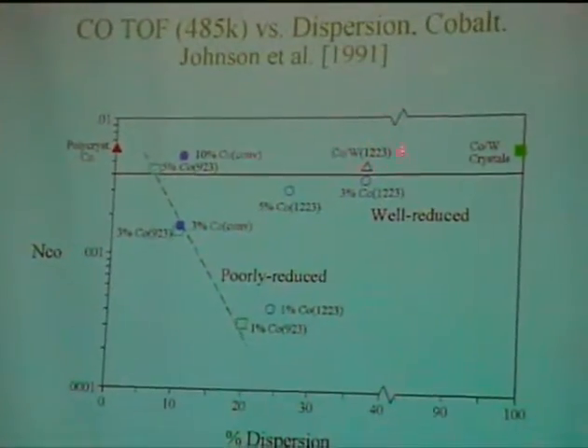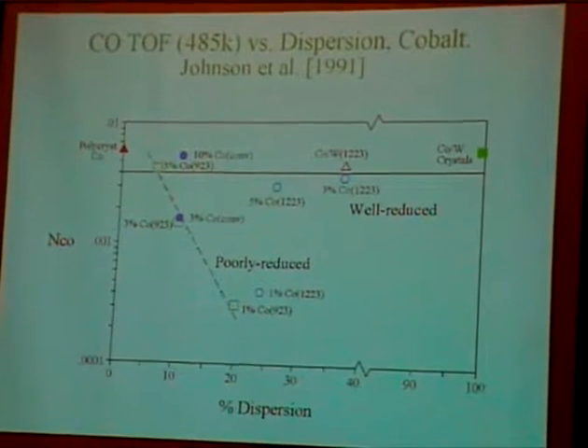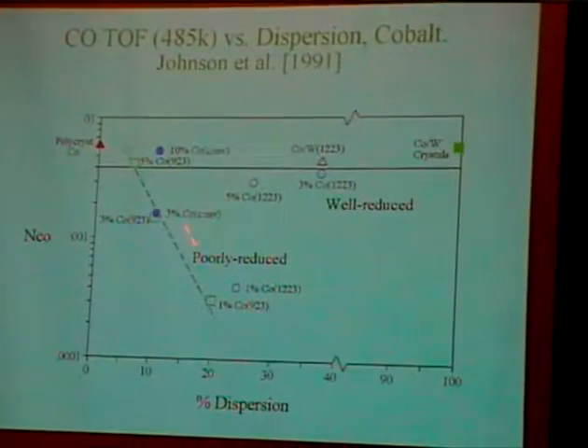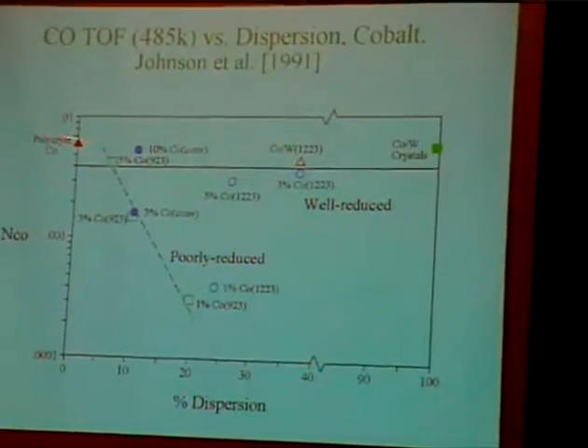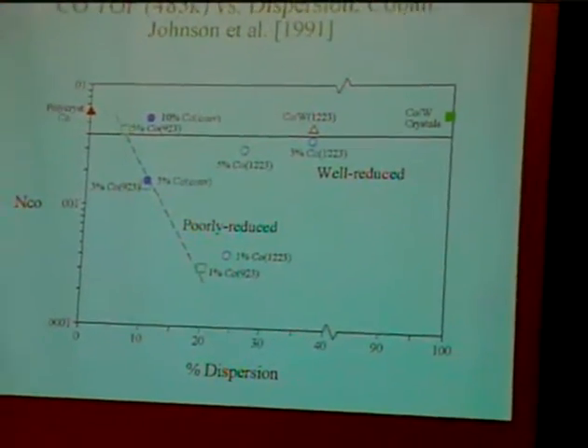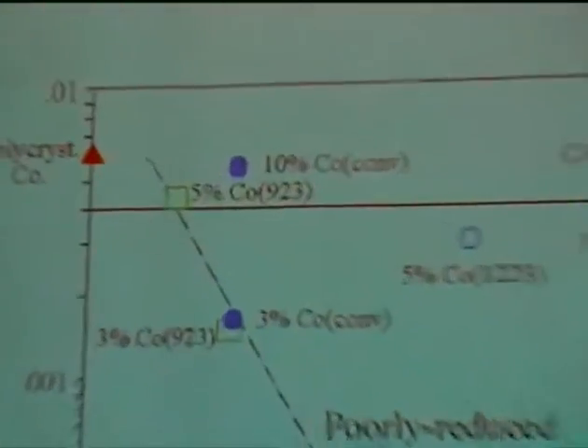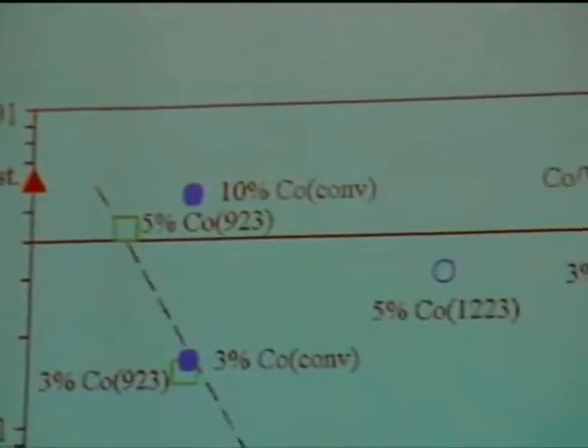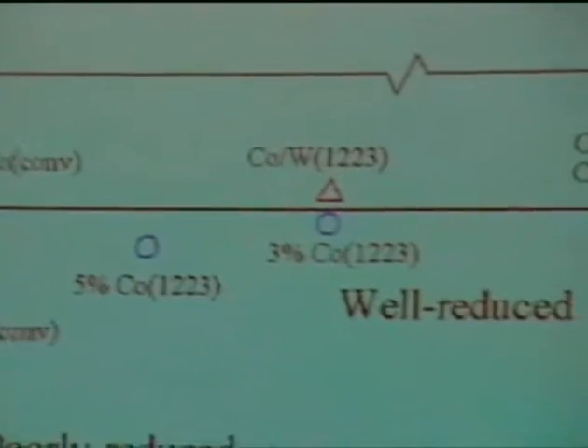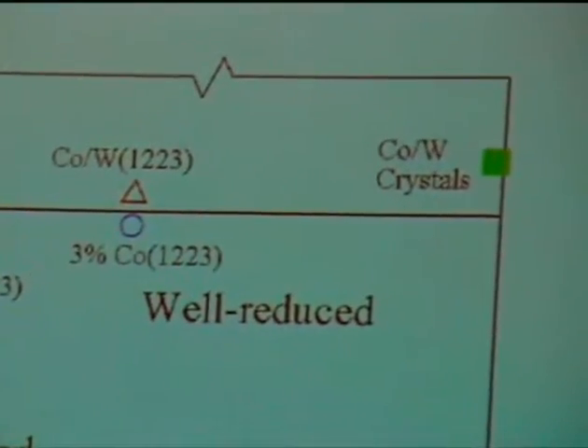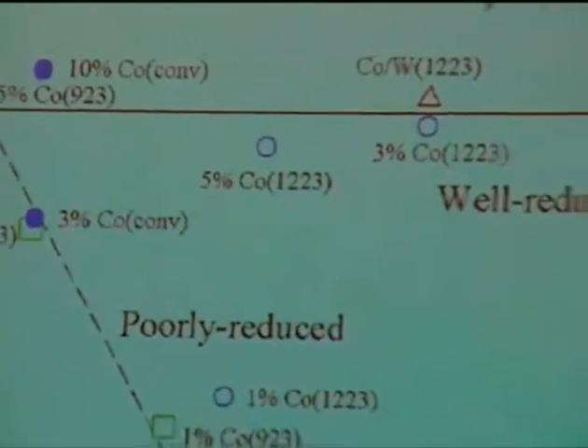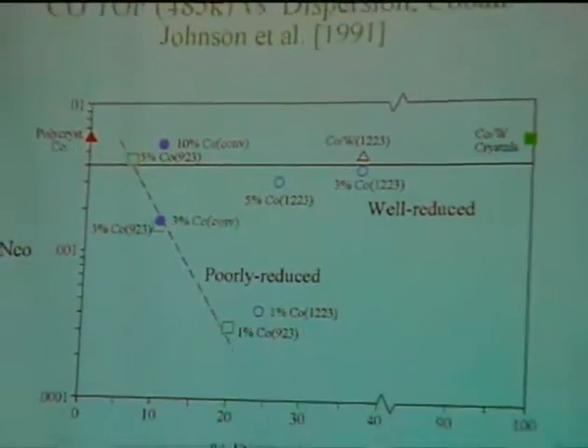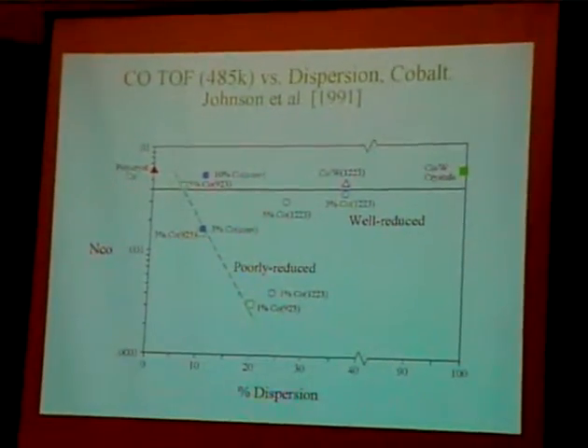This included cobalt catalysts prepared from decomposition of carbonyls with the support dehydroxylated at the temperature shown, over a range of metal loadings, plus polycrystalline cobalt I worked with at Sandia with Wayne Goodman, and cobalt tungsten single crystals that my student Byron Johnson worked with Wayne Goodman. We see two important trends.